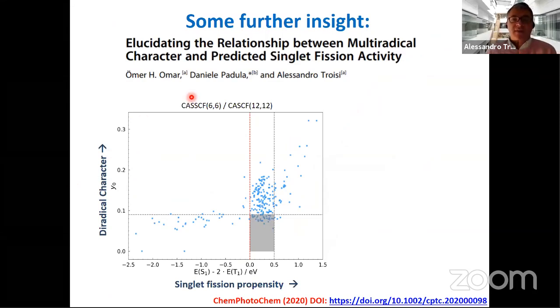Once you have your result, you cannot stop yourself from trying to answer questions that are out there in the literature. And since the literature of singlet fission is dominated by the idea that singlet fission materials are typically biradical, one interesting analysis that you can do is to check if this is true once you have generated a much larger set of potential singlet fission materials. So you can plot the propensity of doing singlet fission versus the radical character, and then the generally acknowledged truth is that materials which are potentially singlet fission materials are in this region, so have good radical character.